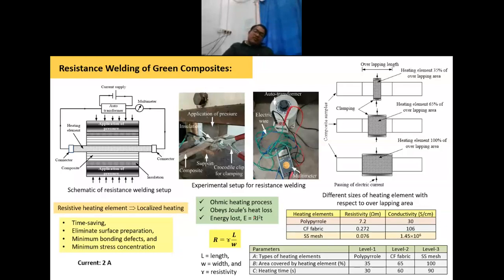So once you apply voltage, it will heat up the surrounding polymers, the material around the heating element. Due to that heating process, the polymer may also melt, if the temperature generation is high enough. Once you apply pressure to the melted polymer, you can create the bond between the two composite specimens. This is basically Joule heat loss, and you can calculate the energy loss using this formula.